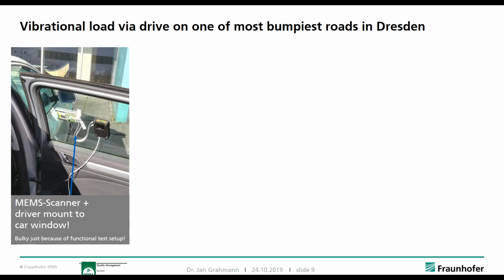In resonance scanners, you use the resonance frequency in order to have large deflections, even for high frequency scanners. Like I said, we go up to 100 kilohertz. So we have 50 and 100 kilohertz scanners that can do 5 to 7 degrees mechanical deflection. That is only possible in atmosphere when you have a high quality factor. That means on one hand, you have a high drive efficiency. And secondly, you can basically not influence the actual trajectory. What you can influence is the amplitude. You can, for example, use the position sensor and a closed loop control to drive a resonance scanner with a constant amplitude, independent of environmental influences. But the trajectory is basically fixed.